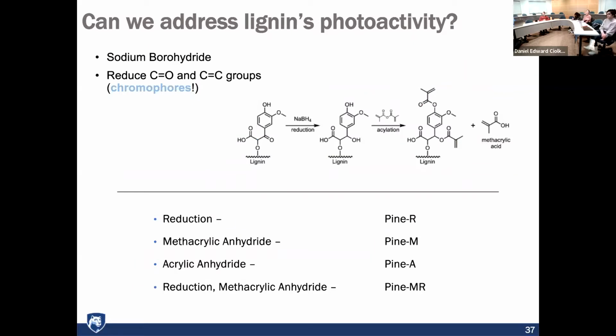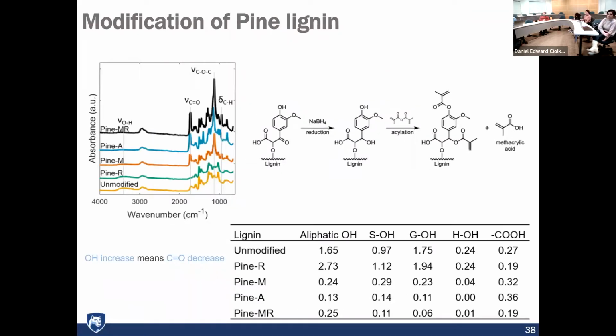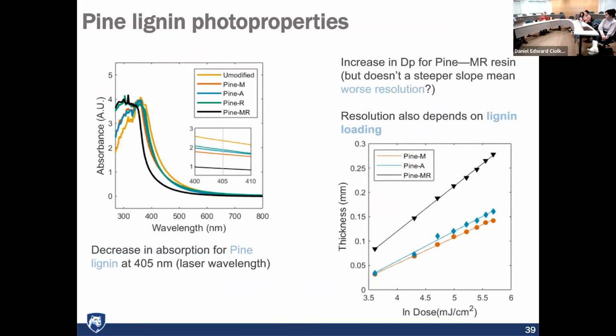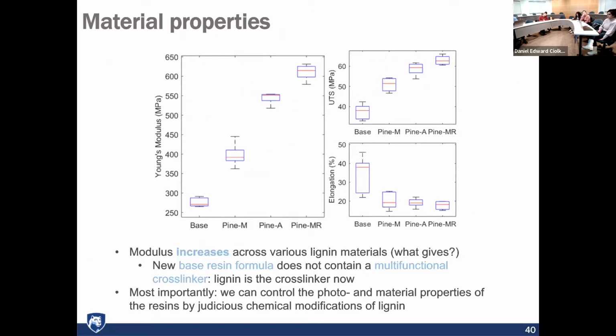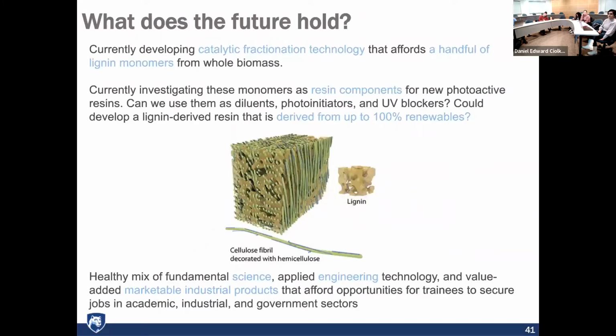And then, I know I'm running short on time here, but the photoactivity of lignin we can change by doing some reduction reactions. This allows us to enhance the photo properties of lignin even more, and gives us, again, more measurements of what's going on in terms of resolution for lignin, which depends on the loading of how much lignin we add. But the material properties, in this case, stiffness goes up, which is good, tensile strength goes up, which is great, and elongation goes down, so the material becomes less ductile, more rigid, all good news.